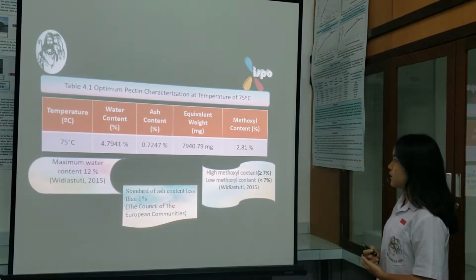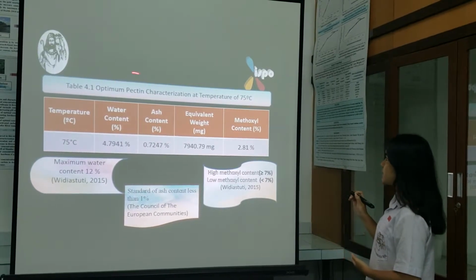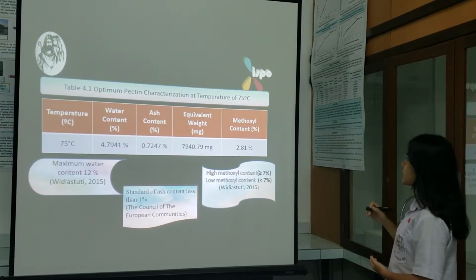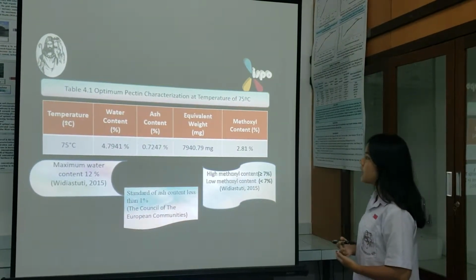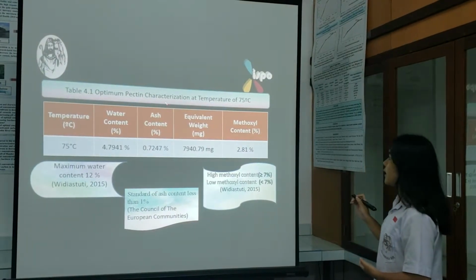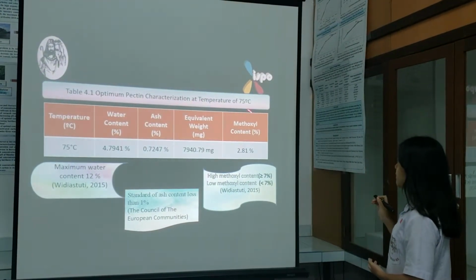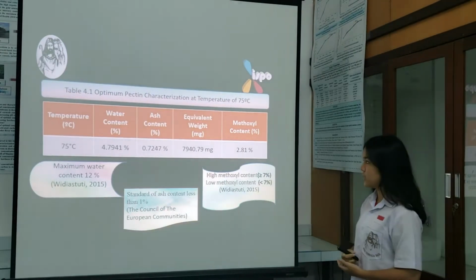From the following table, we can see the optimal Pontianak orange peel-based pectin characterization at the temperature of 75 degrees Celsius, with the values of water content, ash content, equivalent weight, and methoxyl content as follows, has met the standards.